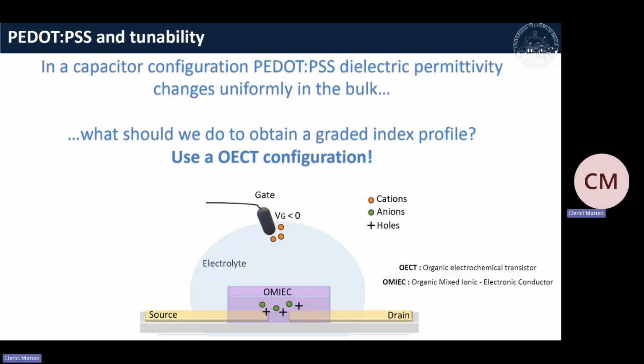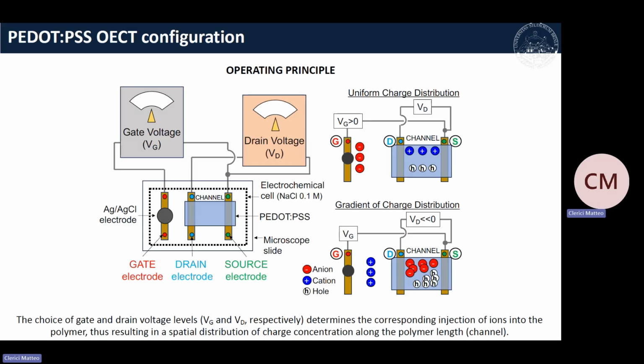So instead of having just the PEDOT, in this case this organic mixed ionic electronic conductor, this OMIEC that you see here, is our channel of the transistor, connected between the source and the drain. If the source and the drain are at the same voltage, you're back at square zero. You're back at what we saw before. With an equal voltage between these two connectors, you equally distribute the charge across the channel, and you change the refractive index properties in bulk. On the other hand, if I apply a voltage drop between the source and the drain, I am able to create a charge distribution, as you do in a normal transistor channel, between the source and the drain. And so my charge distribution will correspond to a different conductivity and therefore a different refractive index profile.